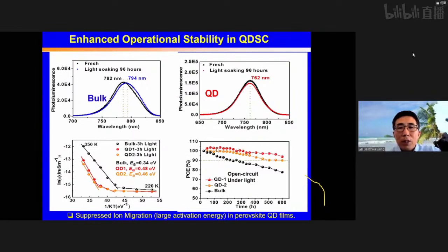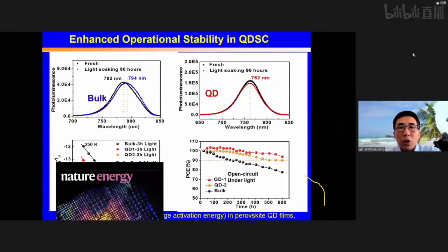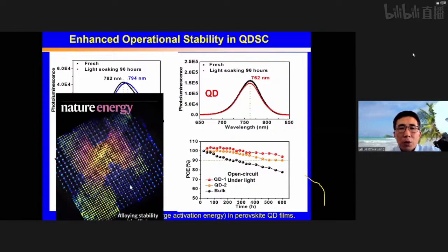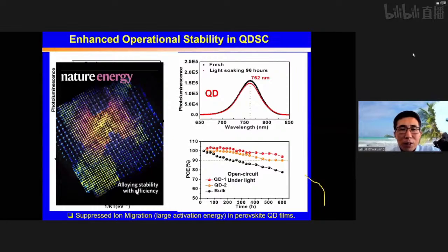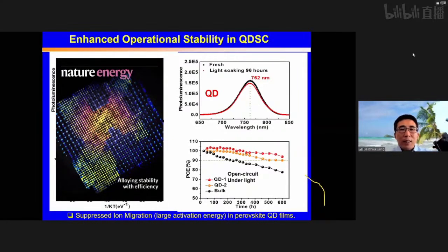And in terms of the long-term stability, after 600 hours under light, we still have more than 90% of the original efficiency. This has also been highlighted by the journal, saying that how to balance the stability and the efficiency of the system is critical.